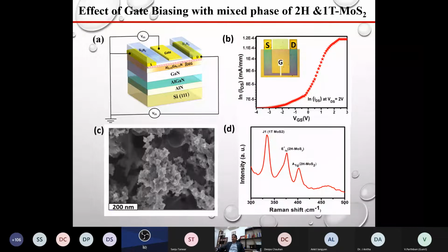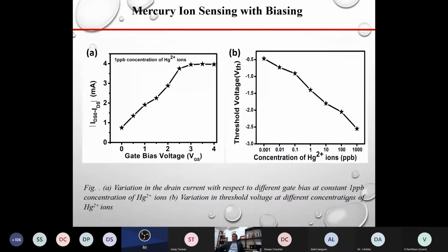So here you can see this one is the gate, and this is the VGS and ID plot. We again confirmed that the 2H and 1T phases exist by doing Raman spectroscopy. And one more thing we have introduced here is the gate bias. In the previous case we had not applied any bias on the gate, but here we have applied the bias also. We have seen the biasing effect, and when we apply the biasing, we can improve this sensing response. Here you can see how much change there is in the current.